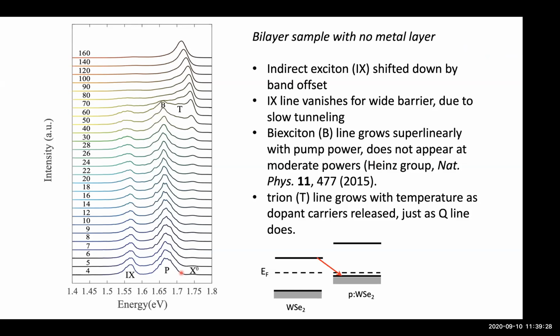Yeah. If you think about the bi-exciton, you have 4 particles, but from their paper, you have a binding energy of 50 meV. Look at the trion, you have 3 particles, but the binding energy is like 30 meV. I don't think a 4 particle system could have a much higher binding energy than the 3 particle one. Oh, we're not saying it's a lot higher.